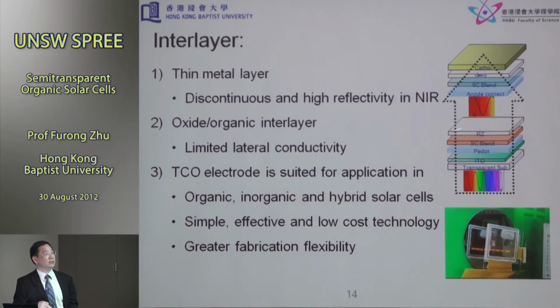And when you stack them together, essentially you need to have an interconnector. This is what we call the interlayer. This interlayer has to be transparent and highly electrically conductive. Otherwise, it won't be able to pass the charges around. Okay. So there are essentially three types of so-called transparent interconnectors. One simple way is to deposit a very thin layer of metal to connect the two cells together. But this has a problem because a metal layer has good conductivity, but in general, if you want this layer to be transparent, it tends to be highly discontinuous, and it also reflects near infrared light.